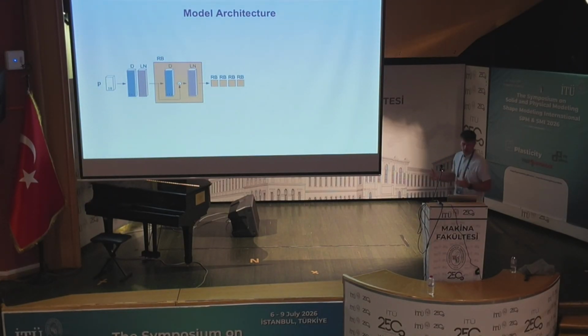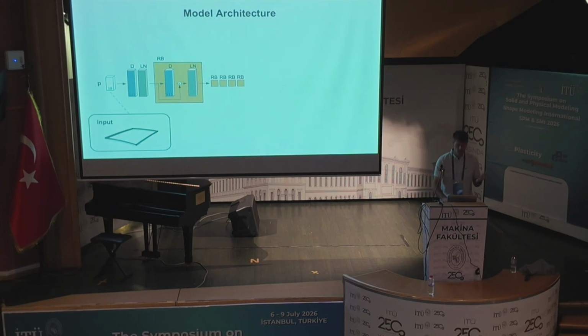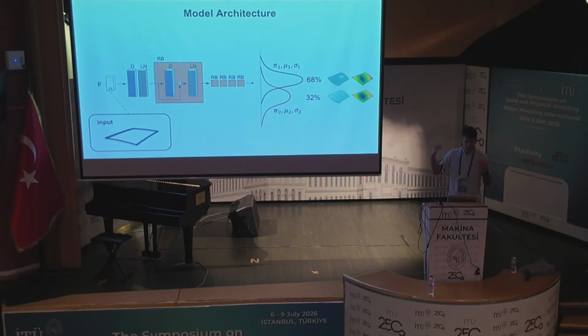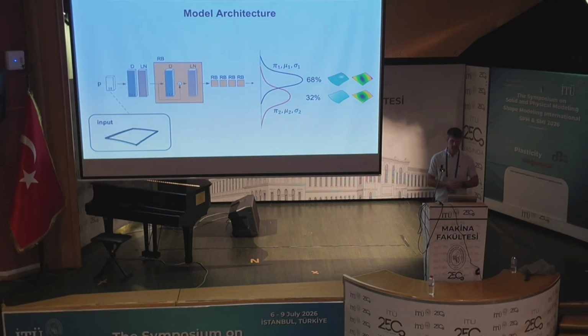Now, these interactive rates are achieved because we trained a relatively simple predictor. The model architecture is a mixture density network. The input is a panel boundary, and as an output, which might be a bit surprising, we have two Gaussian distributions. In each of these Gaussian distributions, the mean contains the interior control points, which define the shape of the bent glass, and the maximal stress of the panel.